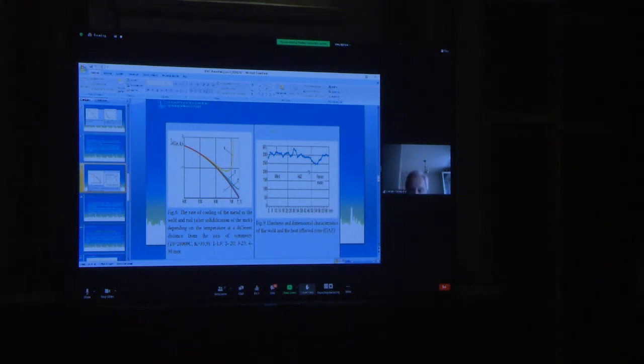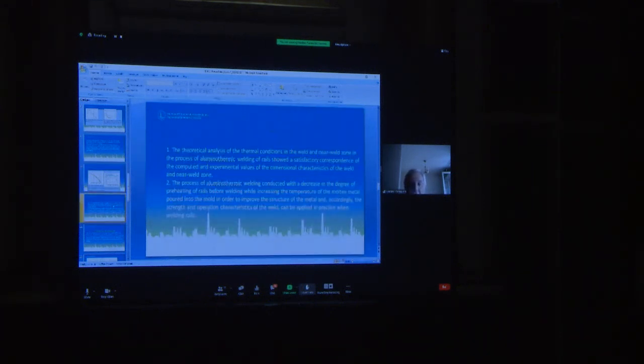The right picture shows hardness and dimensional characteristics of the weld and the heat affected zone. Conclusions: the theoretical analysis of the thermal condition in the weld and near-weld zone in the process of the thermite welding of the rails showed satisfactory correspondence of the computed and experimental values of the dimensional characteristics of the weld and near-weld zone. The process of aluminothermic welding, conducted with a decrease in the degree of preheating of rails before welding while increasing the temperature of the molten metal poured into the mold in order to improve the structure of the metal and accordingly the strength and operation characteristics of the weld, can be applied in practice when welding rails.